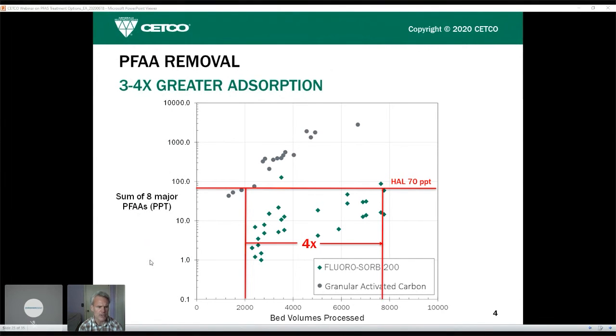And I will note, you'll see a little bit of spread in the data for the FLUORO-SORB in terms of the PFAS or the perfluoroalkyl acids in the column effluent. And the reason primarily is because we are near the detection level for these PFAS. So it took a long time before we really started to see a response in the samples. But this indicates that for these experiments, you would have about a 4 times longer adsorbent life for FLUORO-SORB compared to GAC. Next slide.